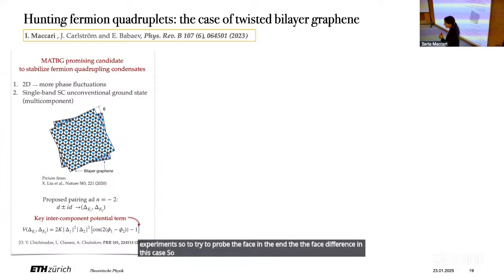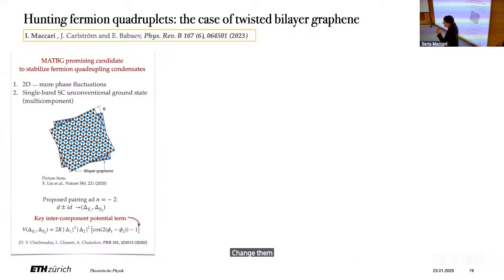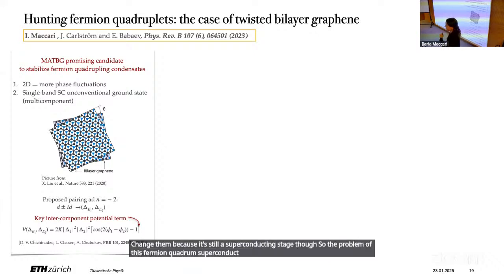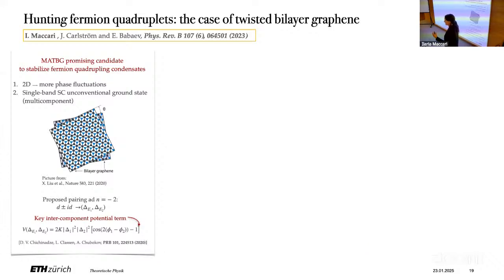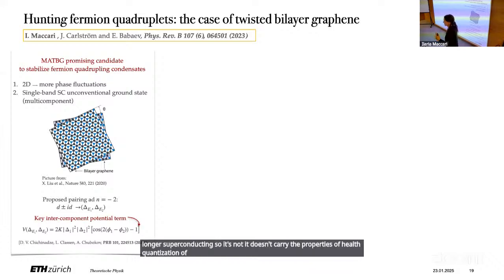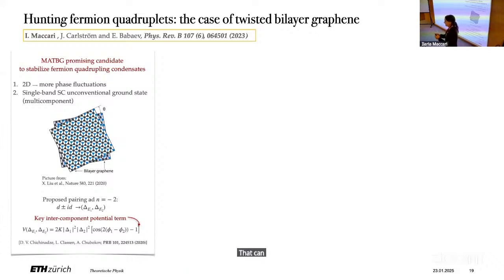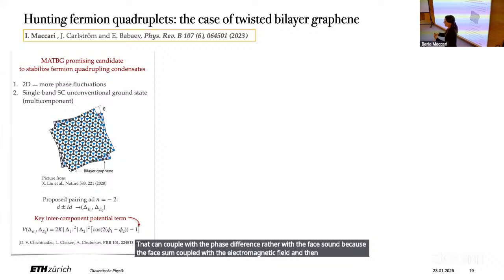For the charge 4e, of course, you can use the fact that the quantization of the flux changes, because it is still a superconducting state. The problem of this fermion quadruplet state, the one I presented, is that it is no longer superconducting, so it doesn't carry the property of half quantization of the flux and so on. So you have to think about some other experiment that can couple with the phase difference rather than with the phase sum, because the phase sum couples with the electromagnetic field, and then yes, you can do experiments to probe the fluctuation of the flux and so on. But with this other kind it is a bit more delicate, I would say.